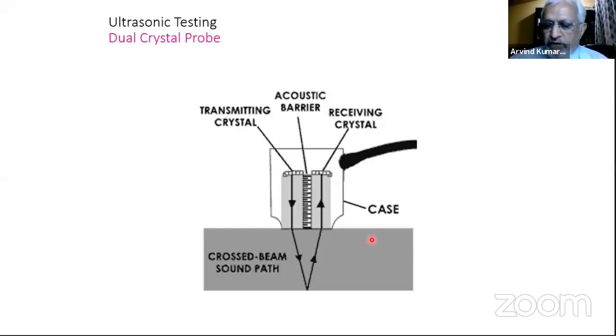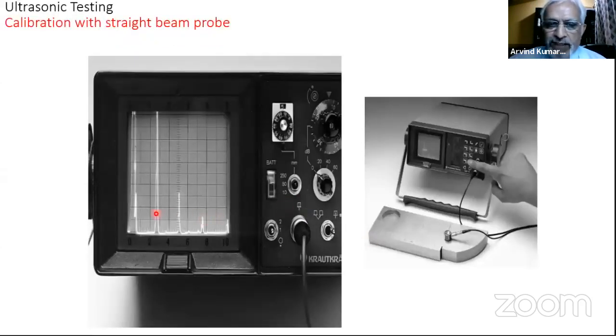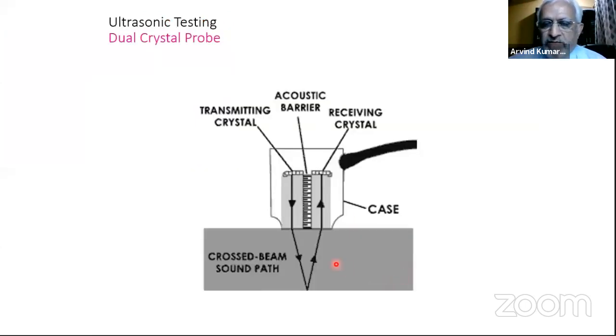So in the earlier case we were using what are called multiple echoes for doing a calibration. For a 100 mm range, we set 4 multiple echoes and got a 100 mm range. The same thing we cannot do here, because with multiple echoes there would be error, because the beam is not going straight, it is slightly at an angle. So this will result in an error.